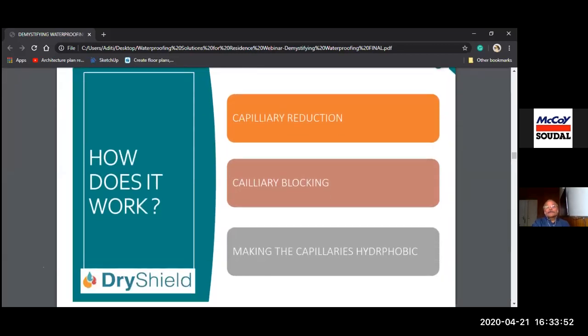So how does it work? It works by reducing your capillaries, capillary blocking, making the capillaries hydrophobic. When you use a crystalline admixture in concrete, a part of it reacts to reduce capillaries by compaction, water reduction, or air entrainment. It also helps in reducing water and allows some air entrainment in the concrete. This makes concrete more compact and denser. The second part is achieving capillary blocking so that all the pores get blocked due to crystallization. Primary and secondary hydration and crystallization block the pores due to reaction with free lime in concrete. Last but not least, crystallization makes capillaries hydrophobic to reduce water transmission.